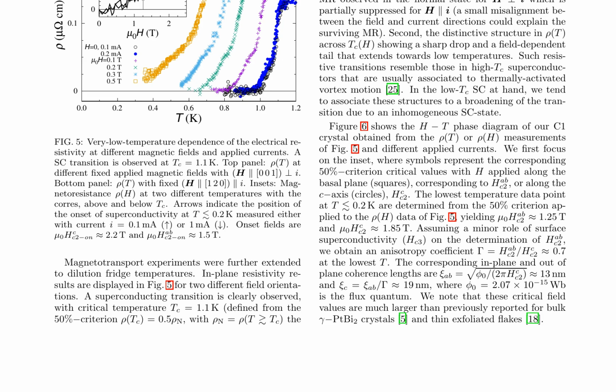This is confirmed by ρ(H) data measured at T ≈ 0.2 K with I = 0.1 mA, depicted in Fig. 5. The H-T phase diagram, presented in Fig. 6, shows the critical fields μ0Hab_c2 ≈ 1.25 T and μ0Hc_c2 ≈ 1.85 T, indicating an anisotropy coefficient γ ≈ 0.7. The corresponding coherence lengths are ξab ≈ 13 nanometers and ξc ≈ 19 nanometers.